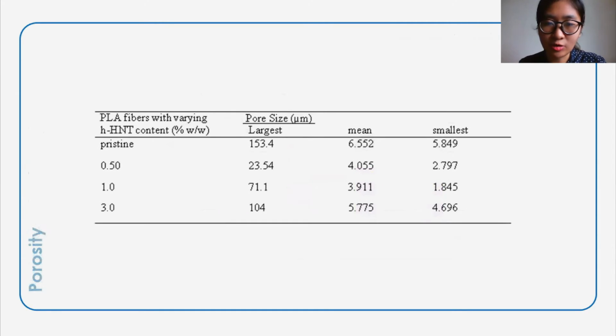So next is assessing the pore size of electrospun composite mats, which connects to the material's air permeability. In this characterization test, airflow at a certain pressure passes through the material soaked in a wetting liquid. The porosity of the fiber mats was measured and is presented here in Table 4. An increase of HHNT content revealed increasing pore sizes. Mean flow pore sizes of 3 to 6 micrometers may provide breathability at the wound site, allowing oxygen molecules to pass through the electrospun fiber mat. This may also increase cell viability and promote wound repair.